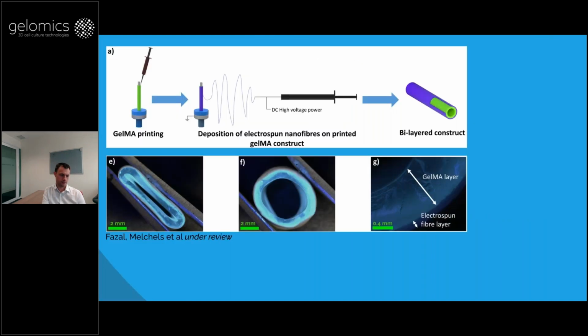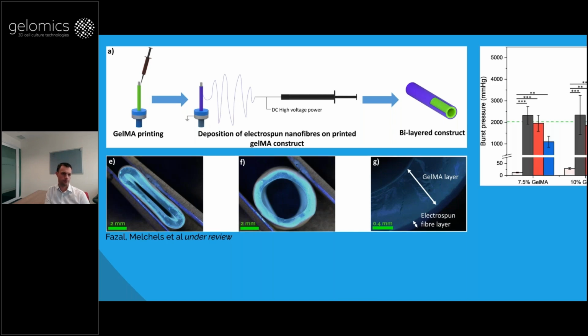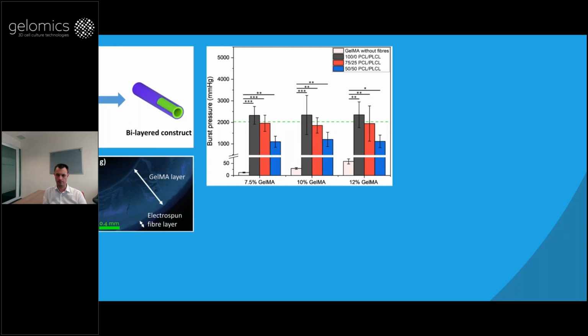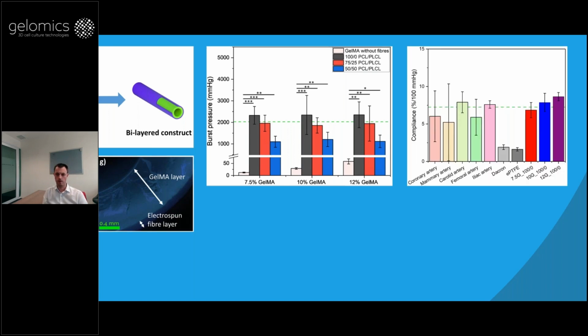This is really recent, just submitted last week. Work with the University of Edinburgh, where we used GelMA in combination with solution electrospinning to make blood vessel grafts. So first printing the GelMA on a mandrel, and then electrospinning a fibrous mesh around it for reinforcement. You can see the GelMA is autofluorescent, so you can see the thicker gel layer and the thinner polymer layer around it. And so we managed to get burst pressures around the same as native arteries, which is the green dashed line. The gel itself would burst at much lower pressures, but the fibers really help to get a good burst pressure. And interestingly as well, the compliance is similar to native vessels.